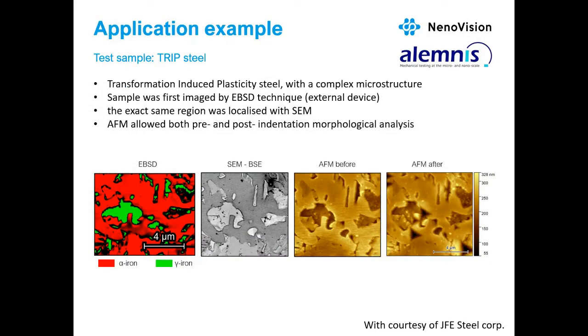There is another example of the transformation-induced plasticity steel. This is a very complex microstructure. Here I would like to show you that it's also possible to use other SEM accessories, not only secondary and backscattered electrons and AFM with nanoindentation, but you can also use chemical analysis such as EDX, EBSD, etc. Because this functionality is not limited, we can really get complex information about the sample surface.